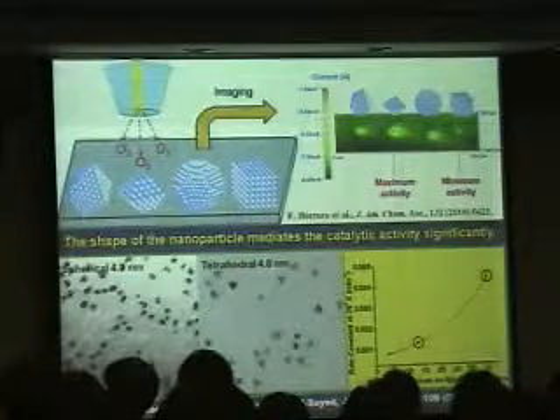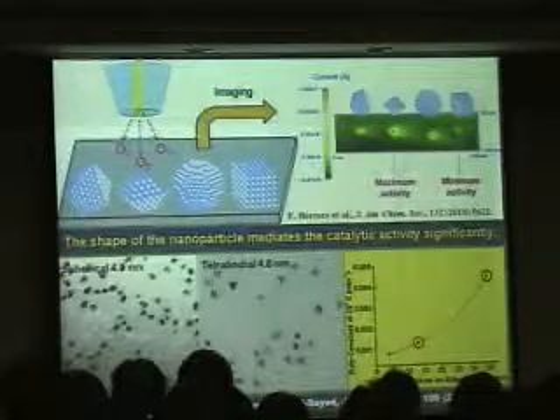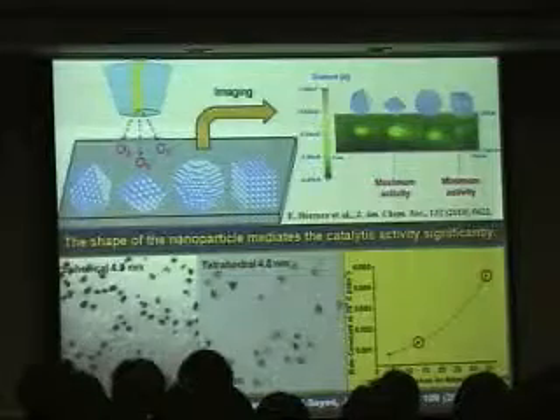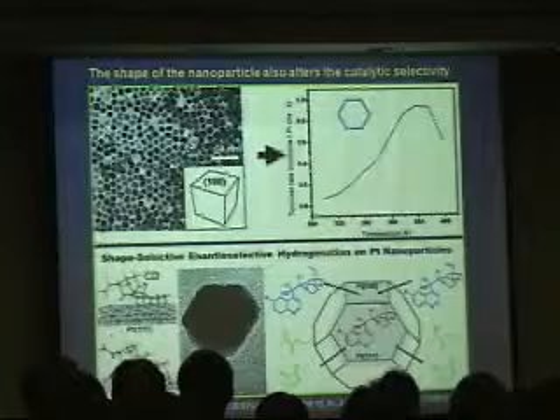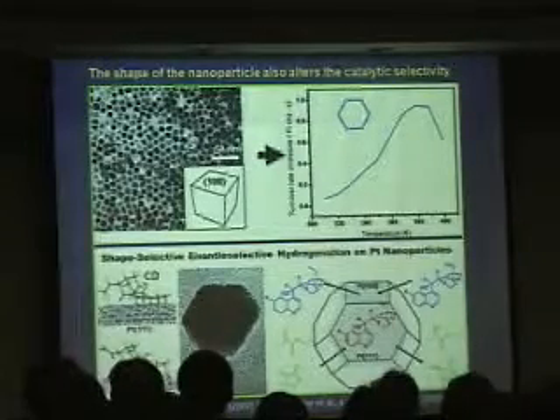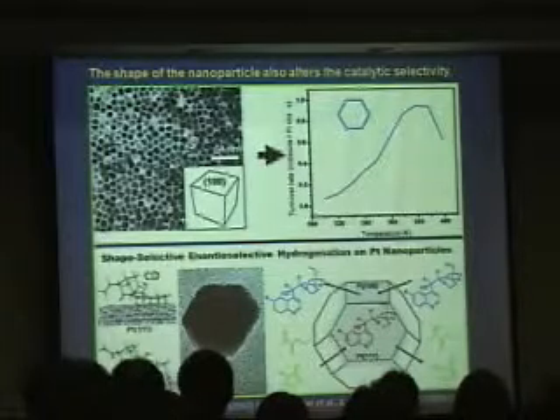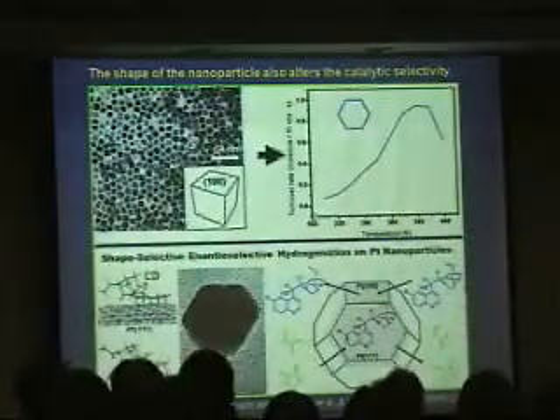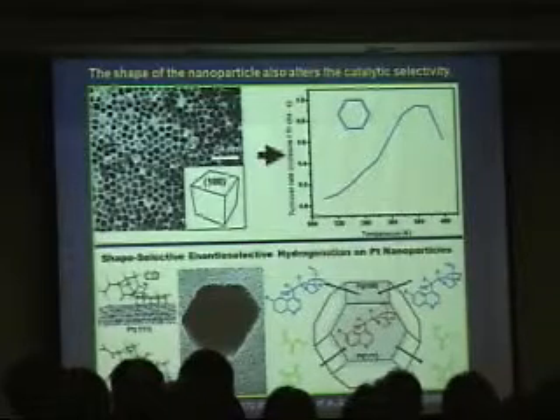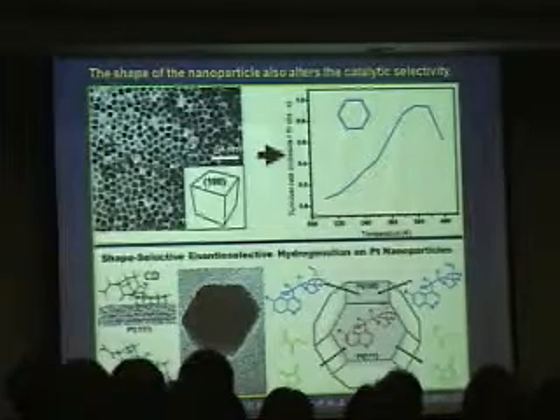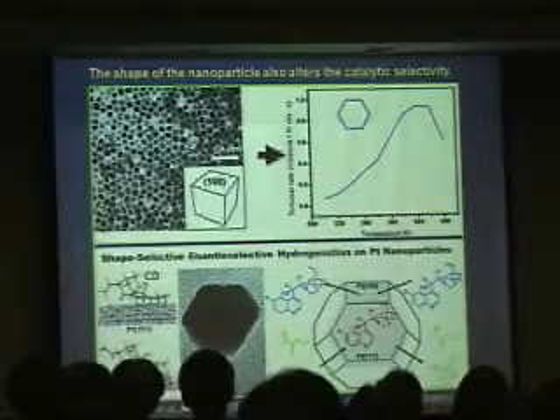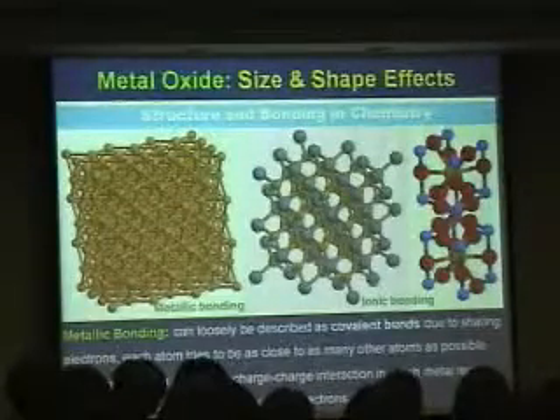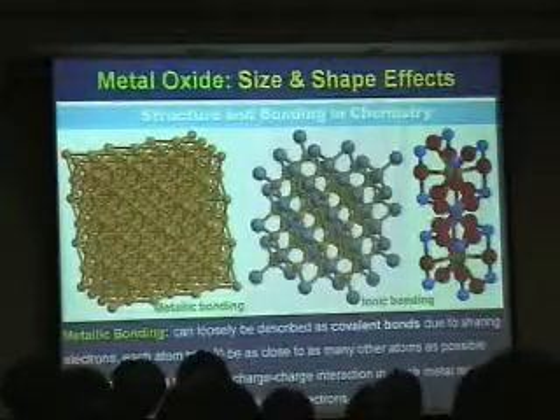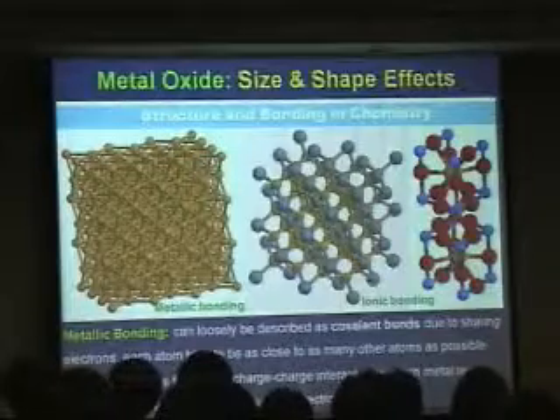Some electrocatalysis also clearly shows this size effect and this shape effect in determining the activity of the catalytic particle. At the same time, as I said, the shape can also change the selectivity of the reaction. For example, platinum cubes used for hydrogenation of benzene are rather different from spherical particles in the selectivity of benzene or some other products. Even for some chiral hydrogenation reactions, the selectivity can be adjusted by the shape of the platinum particles. In those years, this kind of work often appeared in the literature and journals, emphasizing the shape and also the size of metal particles.